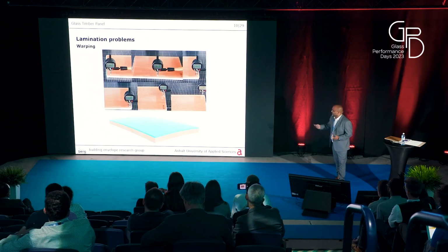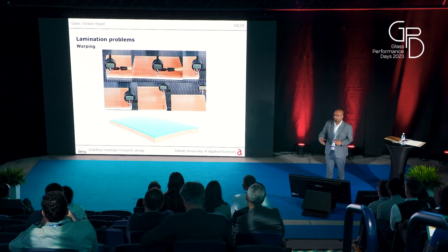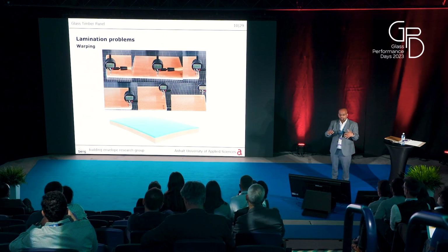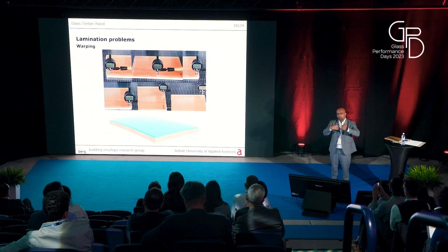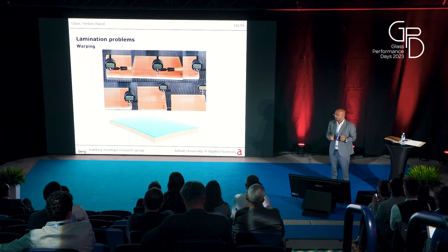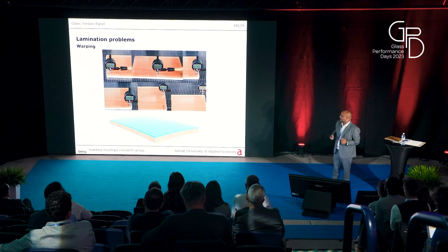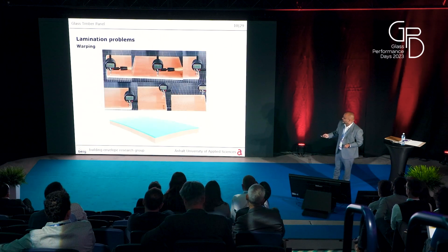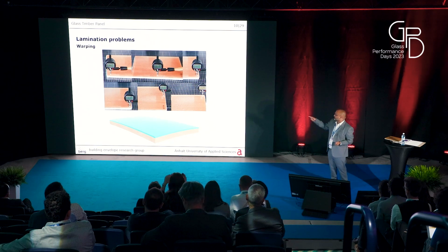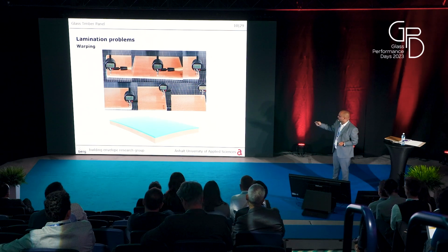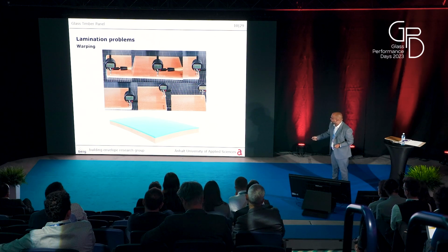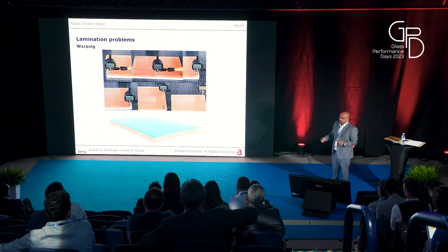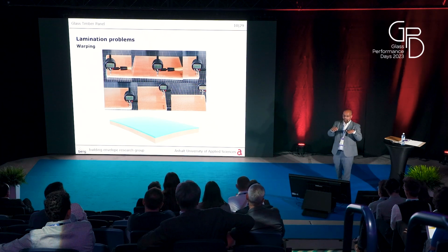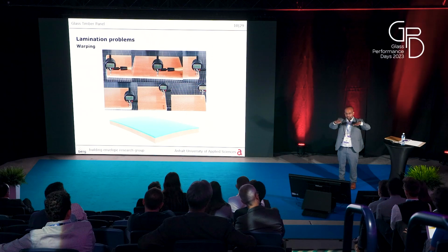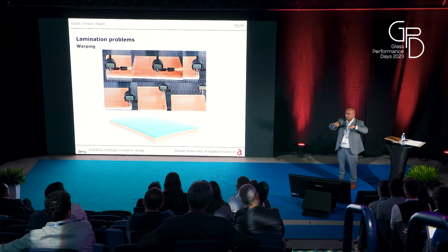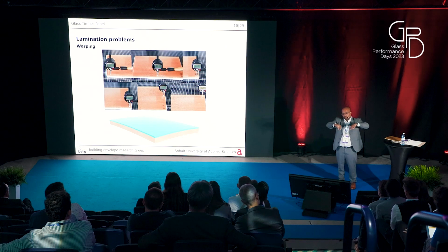And then the most important or hard problem that we faced was warping. Warping is nothing but when the wood absorbs or dries water or loses moisture, it tends to bend on one side or the other side. So this was an example where we used thicker foil again, and you can see that the glass actually broke here too, at the center, because when we use thicker foils, what happens during the lamination is the vacuum bag pushes the corners of the sample, letting the foil squeeze out more of its layer.